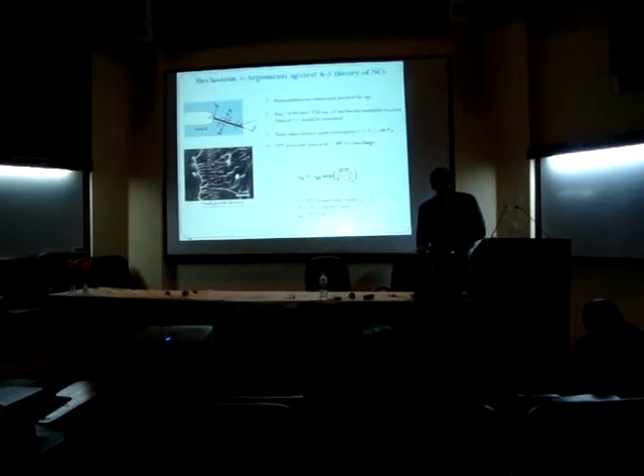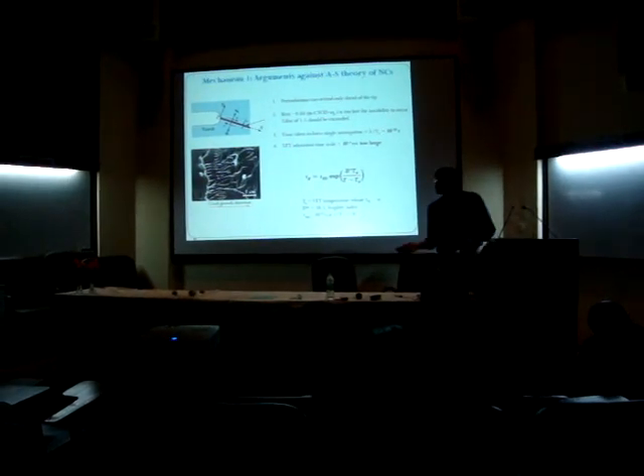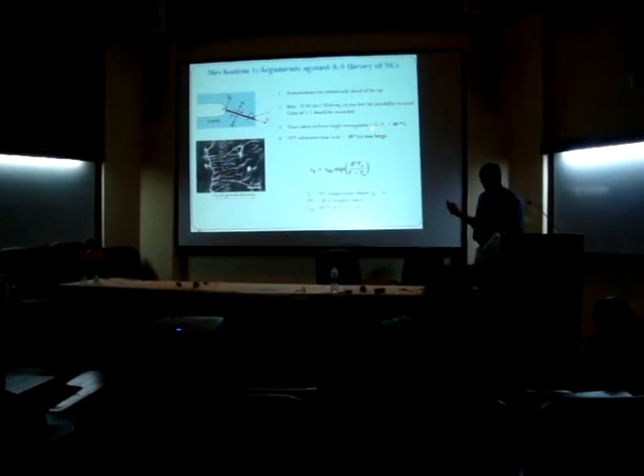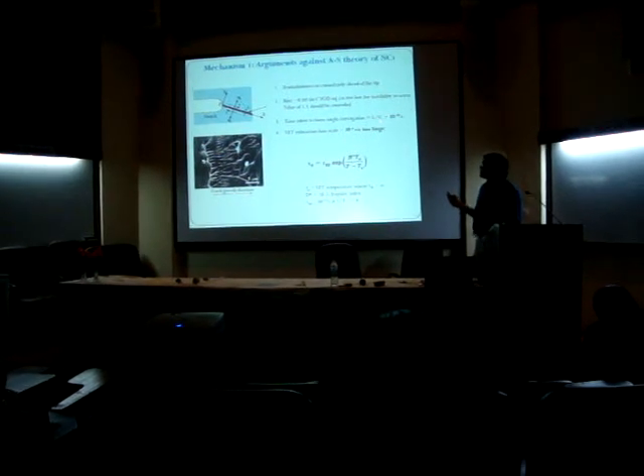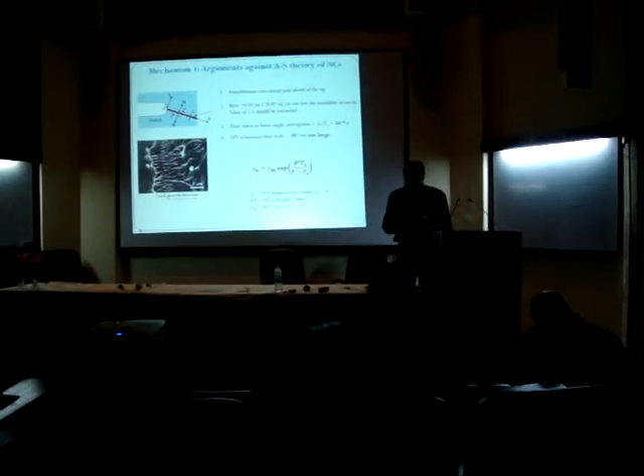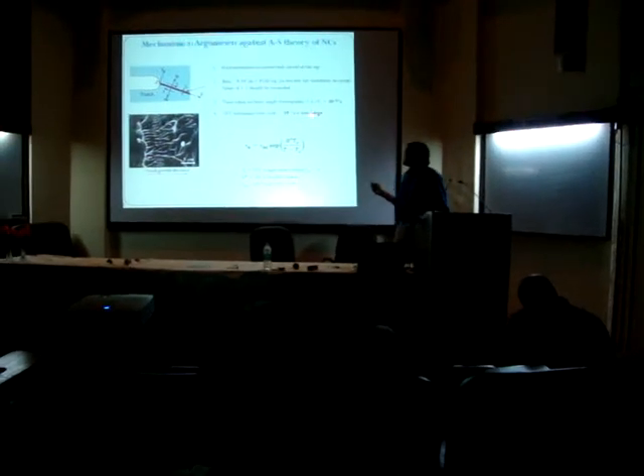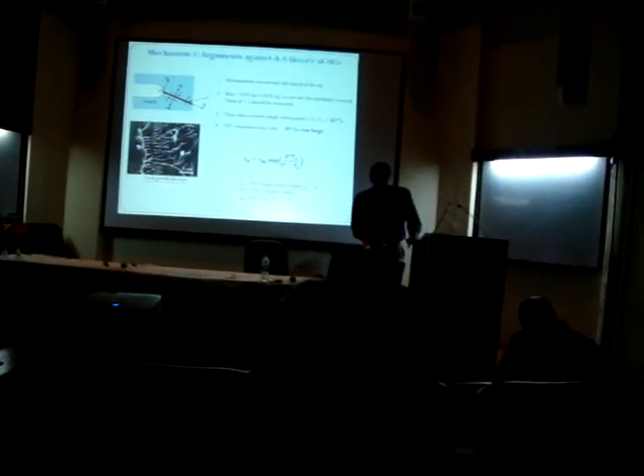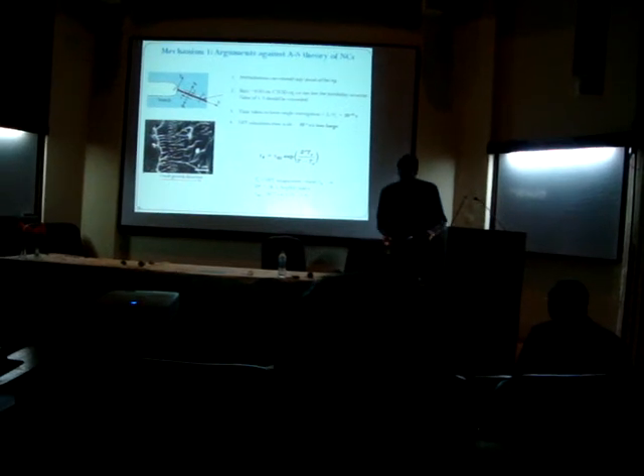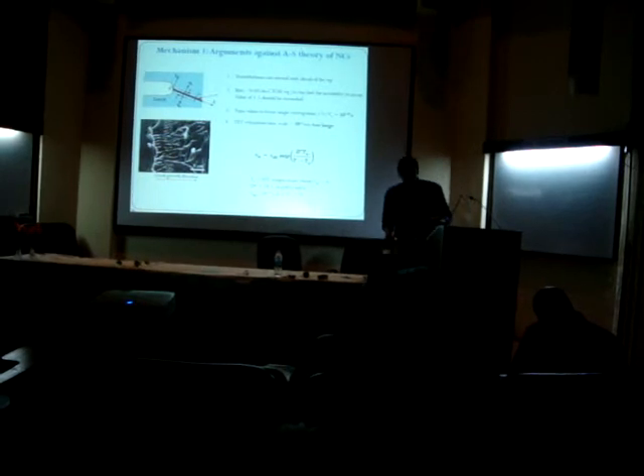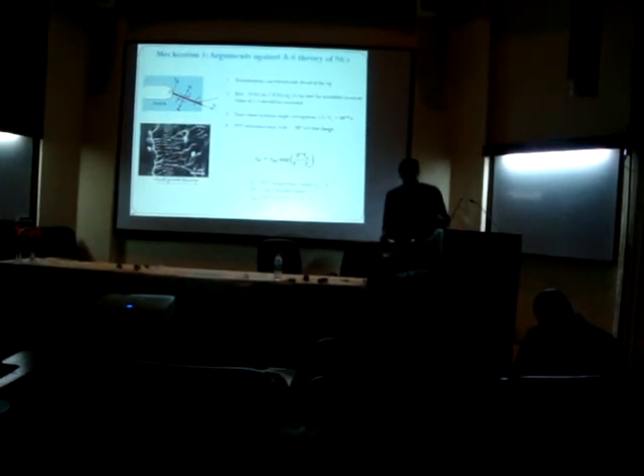We will consider the relaxation time scales that the glass has, and using the velocity obtained using Wallner lines and the wavelength, we know that the crack has to move from one corrugation to the other corrugation in 10 to the power minus 10 seconds. But the relaxation time scale required for the glass to melt, move and relax is actually too large considering the time that is required for a single corrugation to form. So hence we can immediately say that this theory is slightly doubtful.